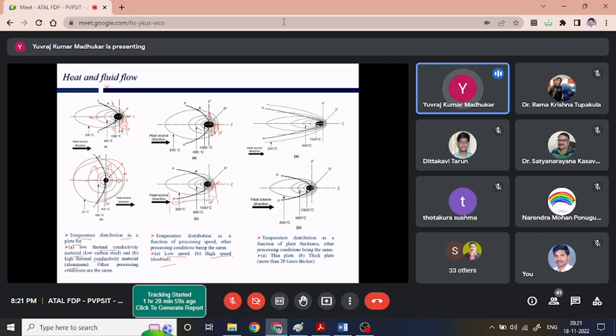With respect to the plate thickness, a thin plate and a thick plate about 20 times thicker. Here we can see that if we have the thin plate, a larger amount of temperature contour is forming on the back side, and very little temperature contour is forming on the front side. For higher thickness of material, yes, there is a good amount of temperature contour forming in the front side. However, again, on the back side we are getting more temperature contour.